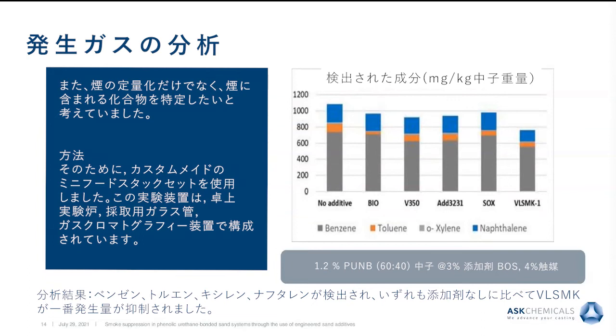On the plot on the right are the results from the experiment. If you look at the y-axis, which is the species found in milligram per kilogram core weight, you can see that the no additive had the higher emissions. Benzene, toluene, xylene are the BTX, and the naphthalene is what people call polyaromatic hydrocarbons, I believe. That's the naphthalene. And there's a lot of studies already done by different people that show these are the highest species. They are kind of concerning for health issues. They are present on the casting process.